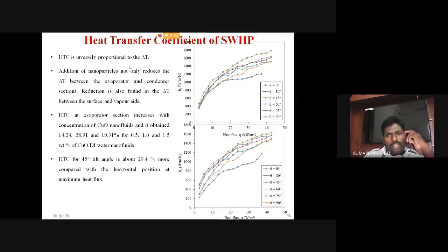Okay. The next one is the HTC of sintered wick heat pipe. The HTC value is inversely proportional to the delta T. The addition of the nanoparticles not only reduces the delta T value between the evaporator and condenser section, but the reduction is also found in the delta T between the surface and the vapor core area. The HTC at the evaporation section increases with the concentration of copper oxide nanofluids, and it attained 14.24, 28.91, 19.31% by varying the concentration.